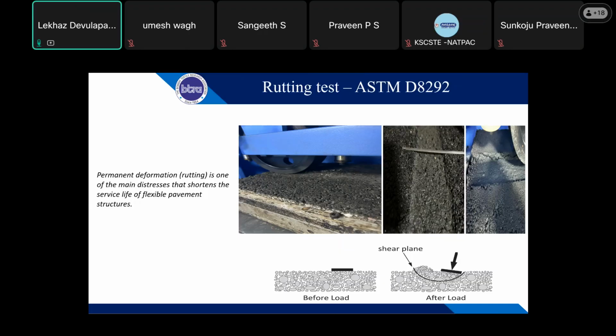So we need to have a test facility. This is called a wheel rut test, and it has been conducted on the composite material, having a DBM at the bottom layer and the geogrid, and then the asphalt BC layer on top of that. You can see the shear failure after the rut test was completed at 20,000 cycles. On the screen we can see there was a crack formation. If your base course or your mix is weak, that will lead to a lot of rut.